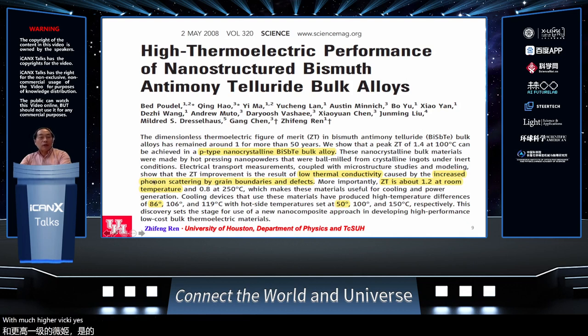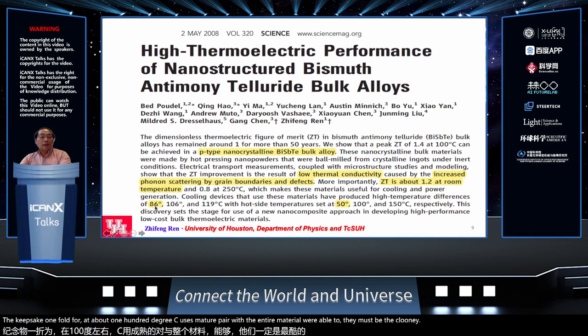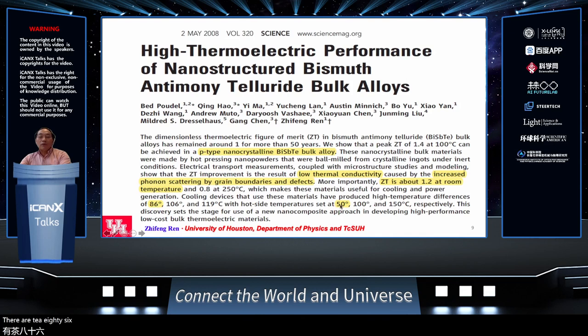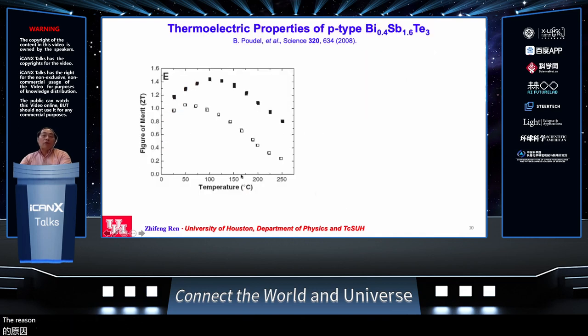Yes, we were lucky. We found that we were able to improve the peak ZT to 1.4 at about 100 degrees C. Using this material pair with the N-type material, we were able to demonstrate the cooling, ΔT of 86, when the hot side is 50 degrees C. The reason for this is because the thermoelectric figure of merit drastically increased.